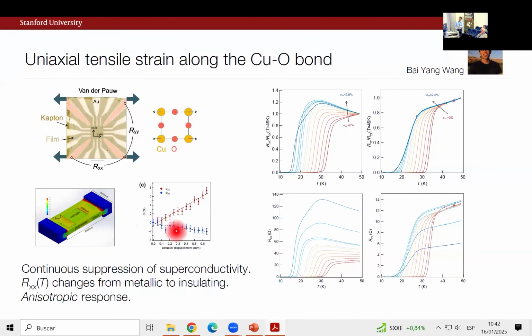And this is using our little microscope inside to track what's happening in the 2 directions. So the point is, if I stretch this guy in one direction, the red curves, indeed, you see this thing stretching, but we have free lateral boundary conditions. So by stretching in one direction, it slightly compresses in the other direction by Poisson ratio, right? And so you can see that here in the blue direction, okay?